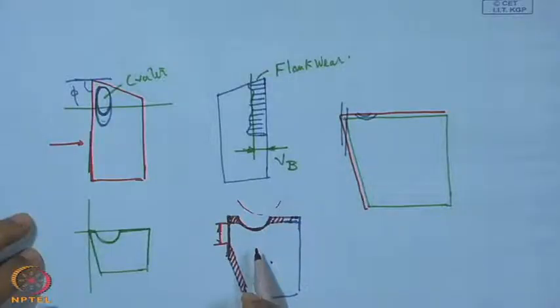So, if we have a proper coating like titanium nitride, then that can also be useful in holding the accuracy of the job. So, what we mean to say is that these tests are essential apart from all screening tests or characterization tests. It is actually the final or ultimate field test which can give us a fair conclusion and clear idea about the suitability of the coating in actual application, and we can find out the potential of various coatings in the particular application area, which may vary from material to material, and can also depend on the process variables, cutting speed, feed, depth of cut, or also the cutting environment, whether it is dry cutting or cutting with some cutting fluid or lubricant or coolant or something like that.